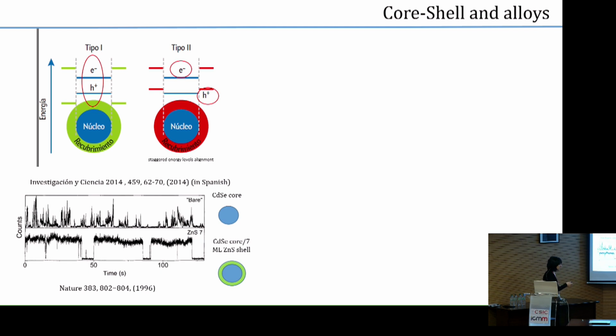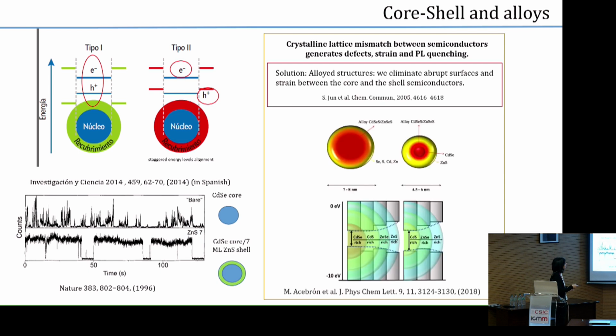So the way to solve that was to produce graded shells, graded nanoparticles, in the way that you can produce nanocrystals which are not composed of abrupt shells, but of graded composition from the core to the shell, and in this way the lattice mismatch is not as strong as to produce defects in these structures.